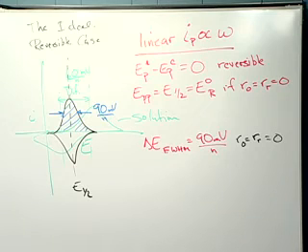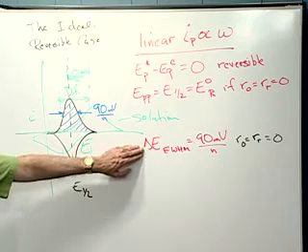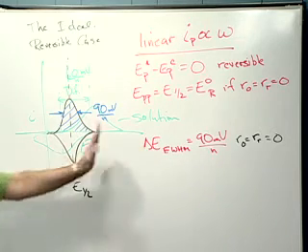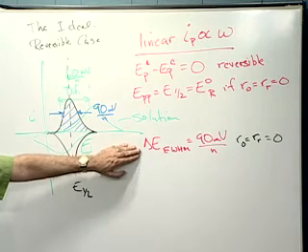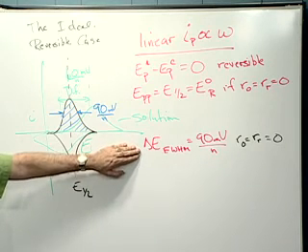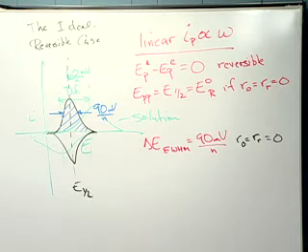I can use the 90 millivolts to figure out if it's on the surface also. But again, I might find a system, in fact, 9 out of 10 systems are broader than 90 millivolts because there are nearest neighbor interactions. So actually, this term is better to use to work on the nearest neighbor interactions. That is, figure out it's on the surface and use this to get the nearest neighbor interaction parameters out of it. And finally, I can figure out how much material is there that is electroactive. I can't say anything about stuff that might be there that is not redox active.